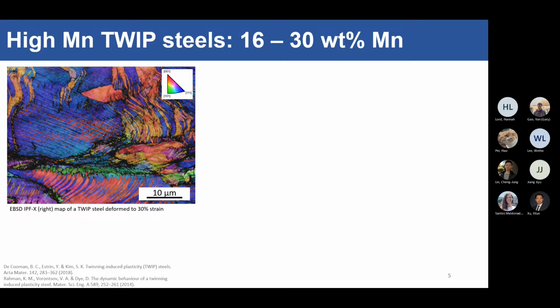Right, so my talk is about medium manganese steels, right, which really implies the existence of high manganese steels. And these high manganese steels are about 16 to 30 weight% manganese and also quite high carbon content, about 0.5 to 1 weight% carbon. And what these steels do is that when you deform them, in addition to dislocation glide, you form these very nice twins. So these twins are very fine, and you see these red lines here in the IPF map. That's actually a bundle of twins. Within that red line, there are even finer twins in there.